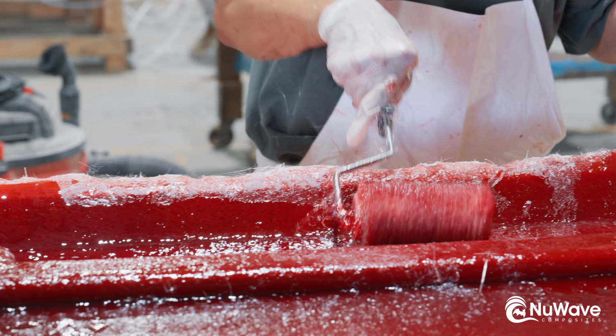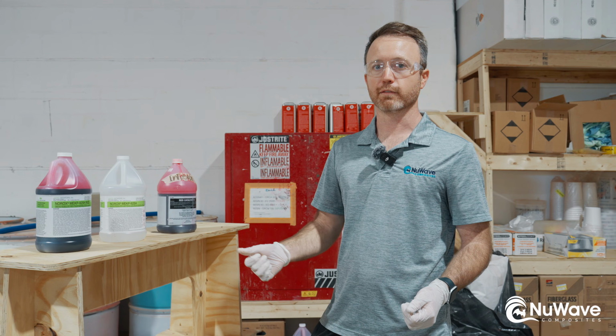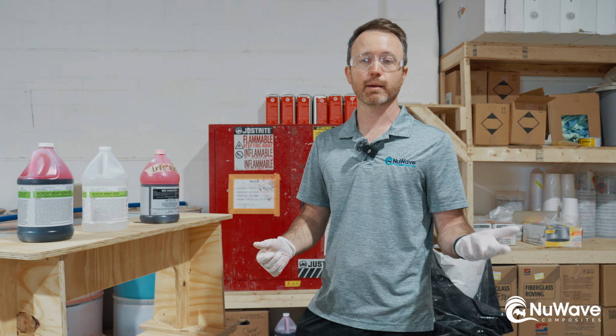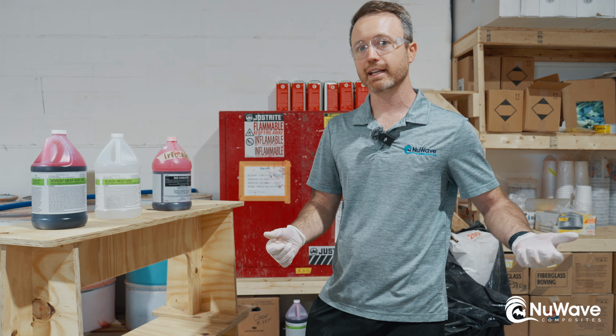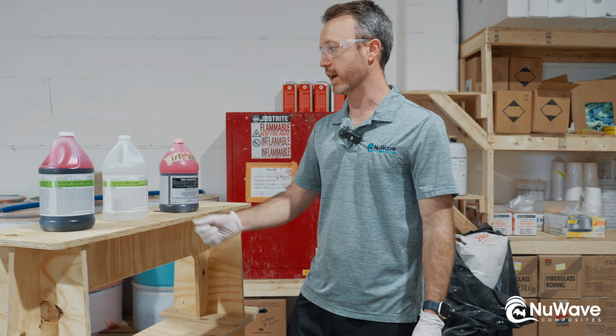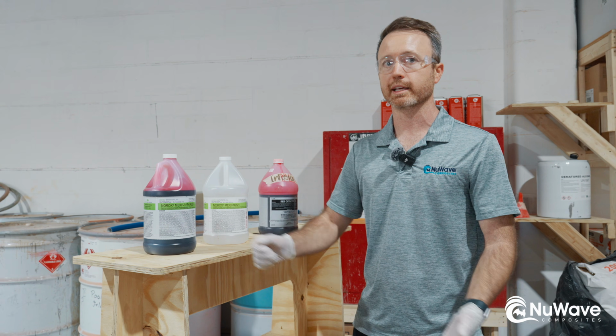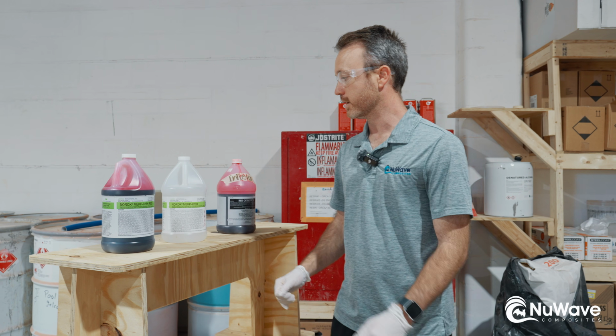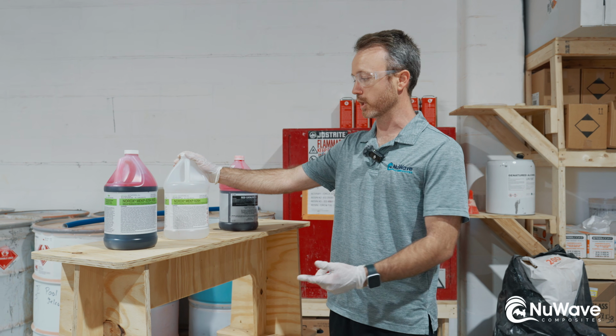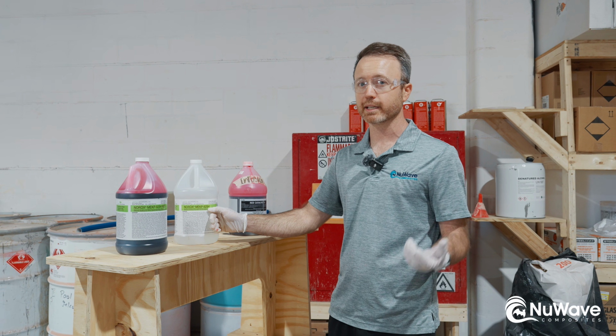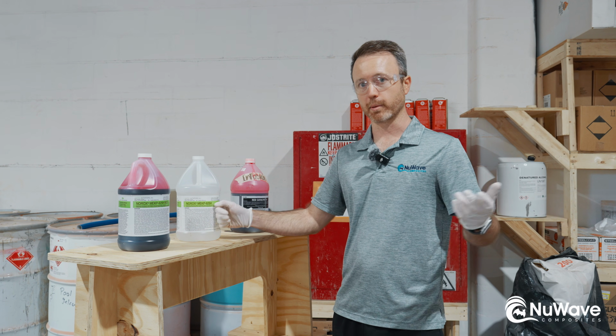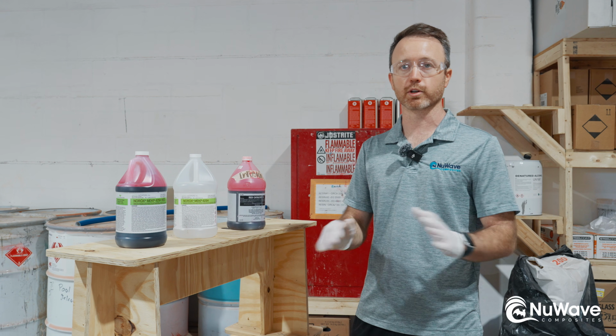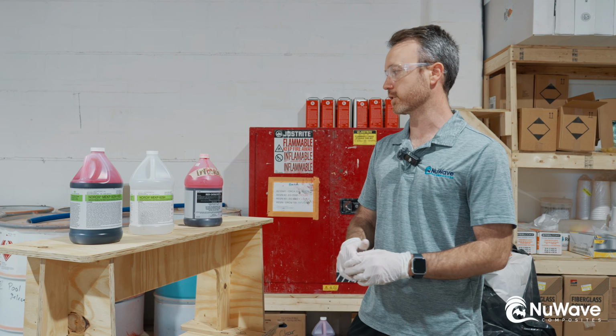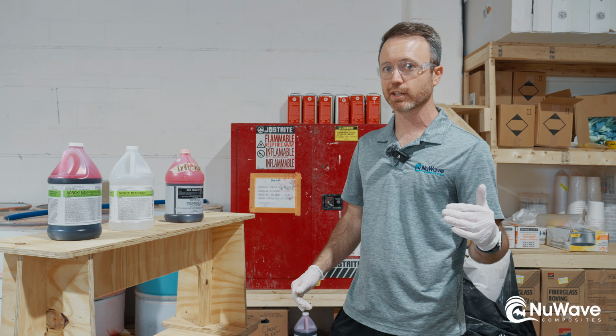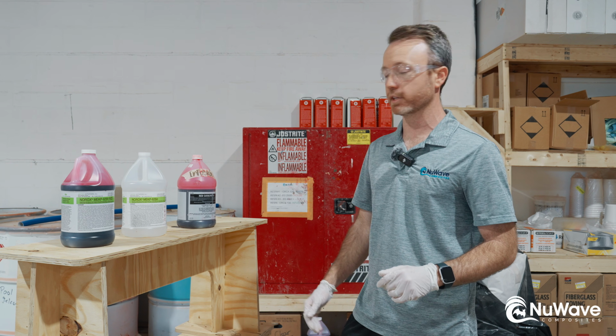One really nice thing about the 925H is that it works really well for polyesters and it works really well for vinyl esters. Vinyl esters have a much different chemical composition than a polyester, and they need a little bit more push to get the cure going. So the 925H is a great product, and it keeps one catalyst throughout the shop. Another really nice thing about the 925H for gel coats is that it helps reduce foaming and can help take porosity out. So the people who have sprayed gel coat, they know porosity is like one of the worst things you can end up with in your part. So being able to mitigate that and keep that a little less common is really great.